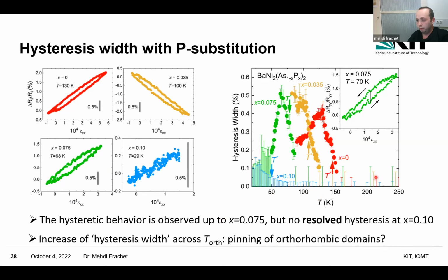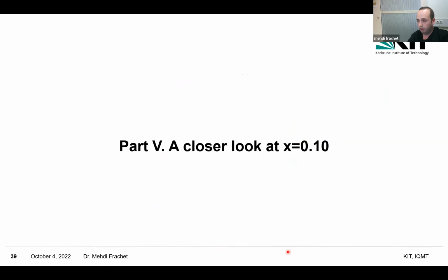But at 10%, we don't see any finite hysteresis anymore when there is no orthorhombic domain. So what it suggests is that at least partially, it could be due to the pinning of orthorhombic domains. Okay, so now, in the last minutes I have, I would like to take a closer look at this 10% sample, which I think is very interesting.